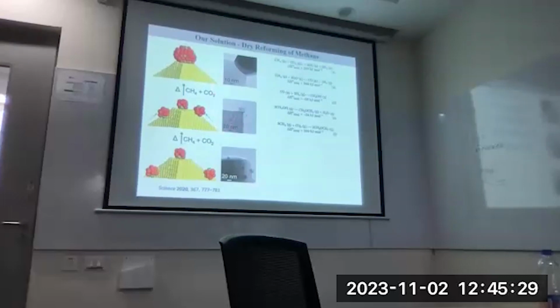But in this case, because we were using this magnesium oxide support and the synergy between this nickel molybdenum and the magnesium oxide, it was burning away the coke and giving us more of this carbon monoxide. We're getting only this as the product. Even the backward reaction is not taking place that much. So we are mostly getting carbon monoxide and hydrogen.